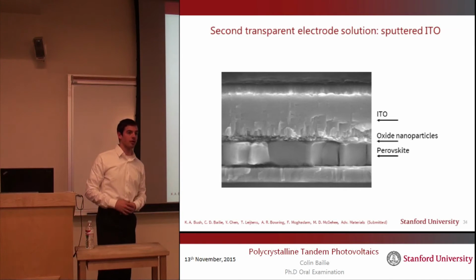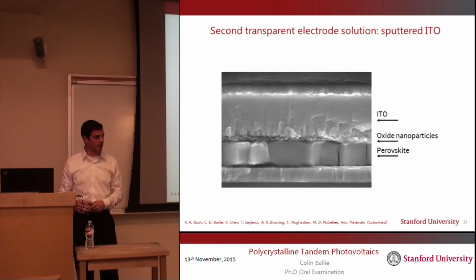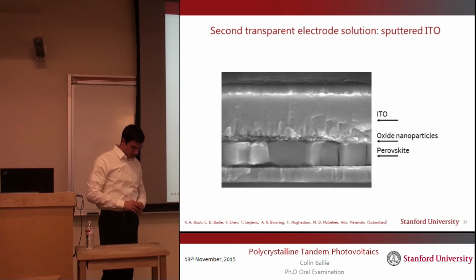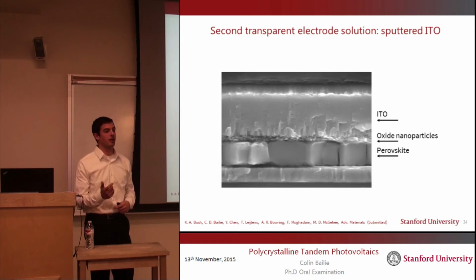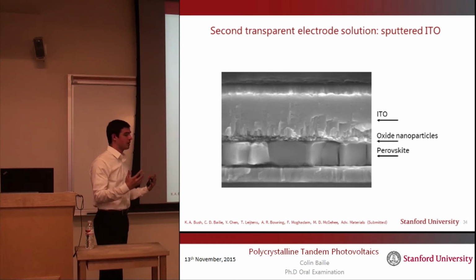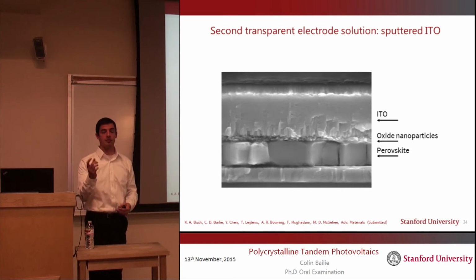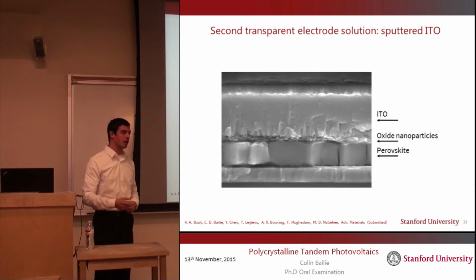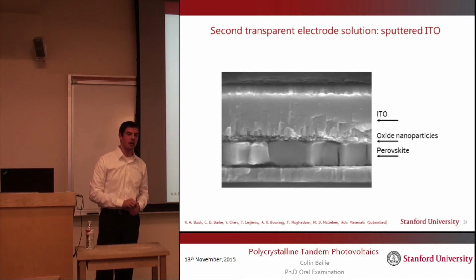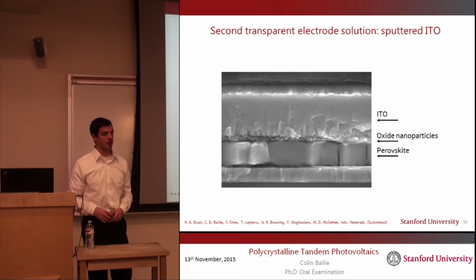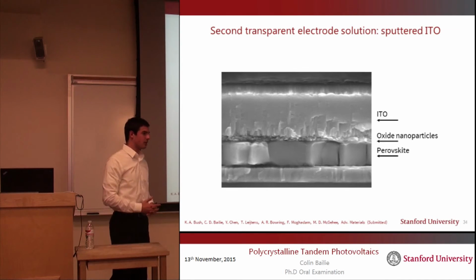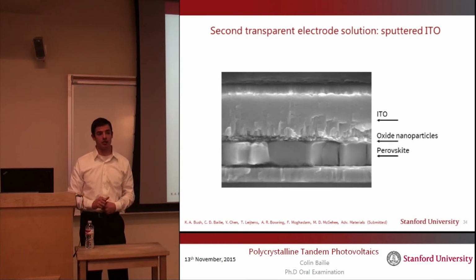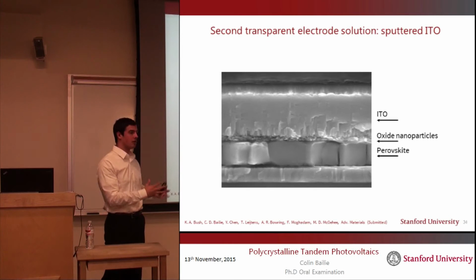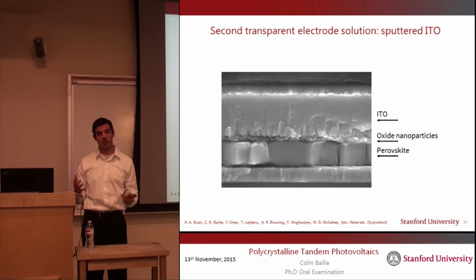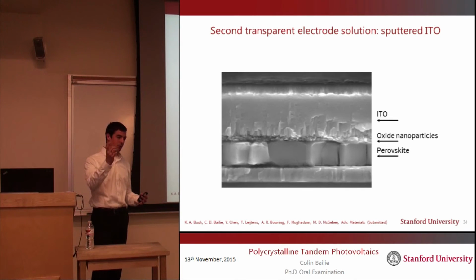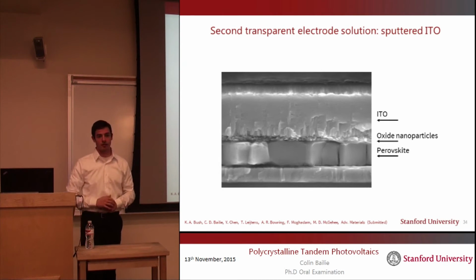And it's already well known for its ability to block moisture in its gas form. What was difficult was that the way you deposit ITO is by sputtering. And sputtering is an inherently damaging process if you're going to try and sputter onto an organic layer. And the perovskite itself, and usually the heterojunction layers on either side, can be considered as organic layers. So in order to avoid damaging the perovskite and its organic heterojunctions, we deposited by solution a layer of oxide nanoparticles. And these oxide nanoparticles provided a buffer in between the sputtered ITO layer and the sensitive organic layers underneath.